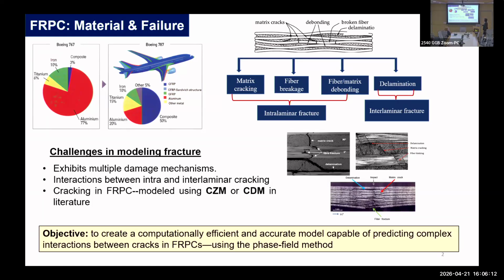The complexity arises from the underlying micromechanics involving matrix cracking, fiber breakage, fiber matrix debonding in the lamina level. And most often these composite materials are used in laminate forms, where basically individual plies of single fiber orientation are stacked together like this. And then the interface between two successive lamina also promotes some failure mechanism called delamination. And most often this interlaminar fracture or delamination interacts with this intra or bulk level fracture mechanism, depending on, of course, the ply arrangement, external loading conditions, and the properties of individual constituents such as the fiber volume fraction, the